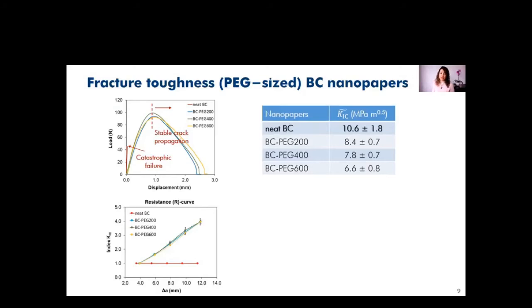In the case of the resistance R curve, what we will measure is the further resistance of the crack to grow. And in the case of the neat BC, there is a flat curve, and that means that while the crack is propagating, there is no further resistance of the material for the crack to grow, because that resistance is constant. However, in the case of the PEG-sized BC nanopapers, while the crack is propagating, there is a further resistance to be overcome for the crack to